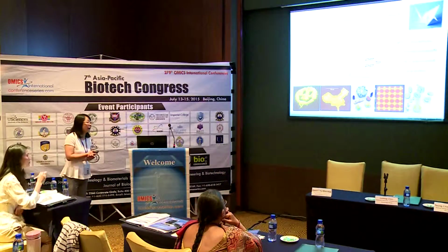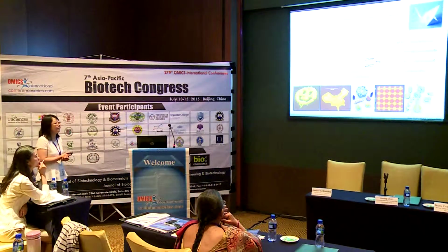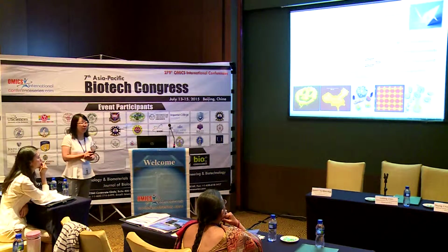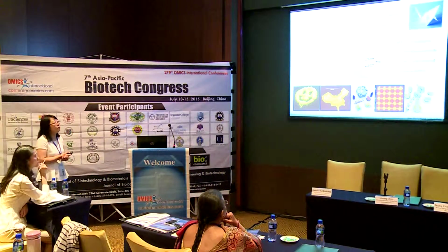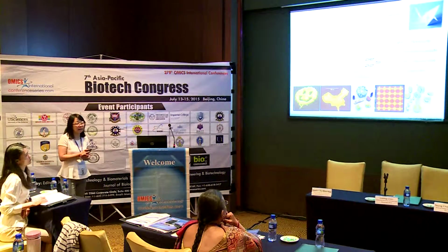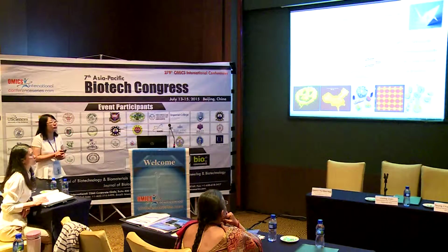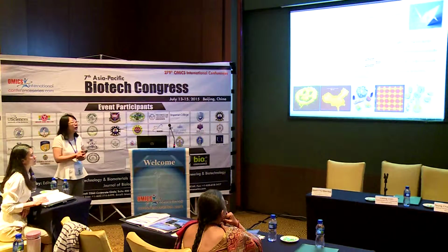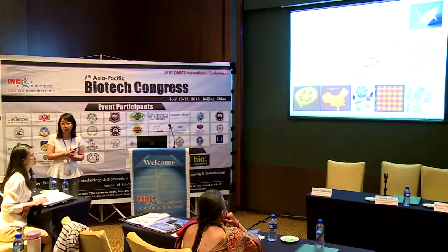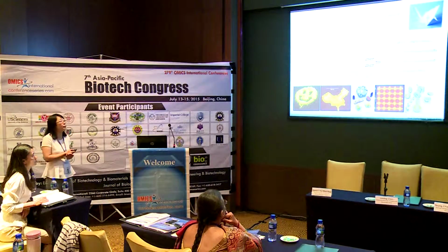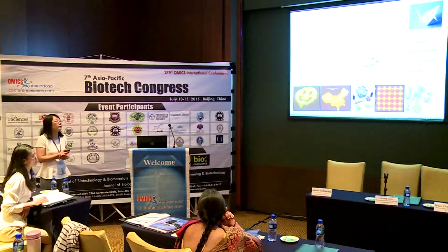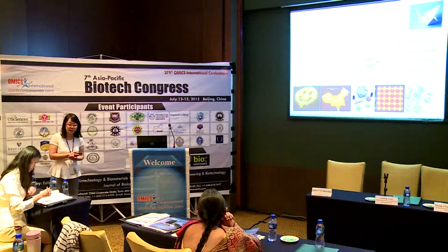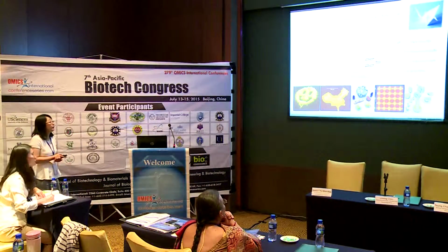made from DNA origami. This is a map of China. And this is a DNA origami 2D array and all kinds of beautiful 3-dimensional structures. The advantage of these DNA origami nanostructures is that they can expand DNA nanostructures to about 100 by 100 nanometer scale. Since we have more than 200 staple strands, each of them can be modified, so we can bring the resolution down to 6 nanometers. We can really manage everything at the nanometer scale.